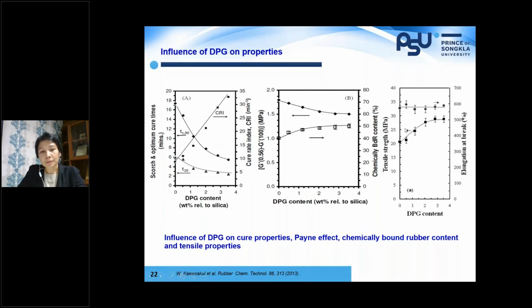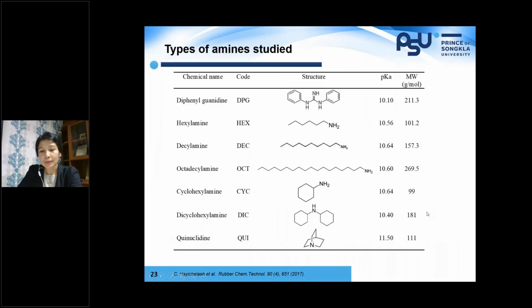So based on this work, and also the work on synthetic rubber, based on solution SBR and BR, we need about 2% by weight relative to silica of DPG in this silica compound. So we took different kinds of amines to investigate, including aliphatic amine and cyclic amine having different molecular weights, and having DPG as the reference.